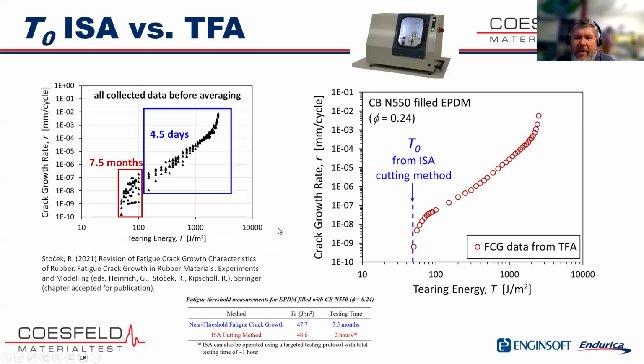Now I mentioned that there's other methods for measuring fatigue threshold. The most obvious method is to actually just do crack growth tests. And so on the left here, this is for the control material that we use in our work. It's an EPDM compound. What I want to show you here is that if you're going to use the direct method for measuring threshold, the crack growth tests that you have to run are crazy long.